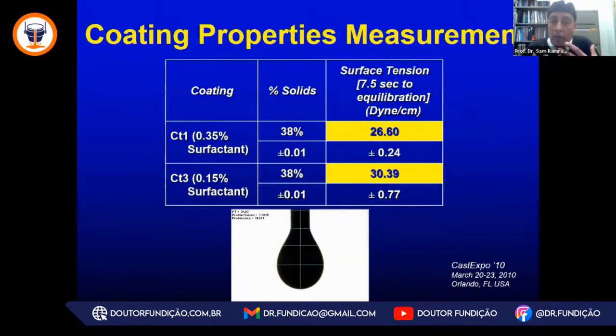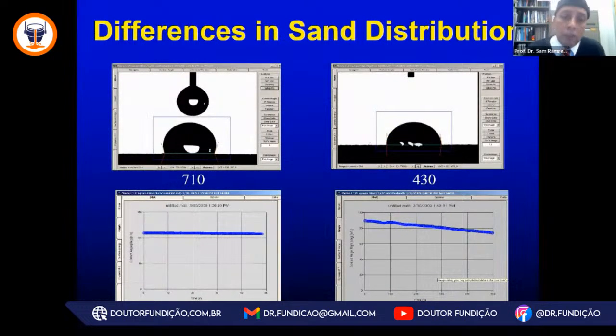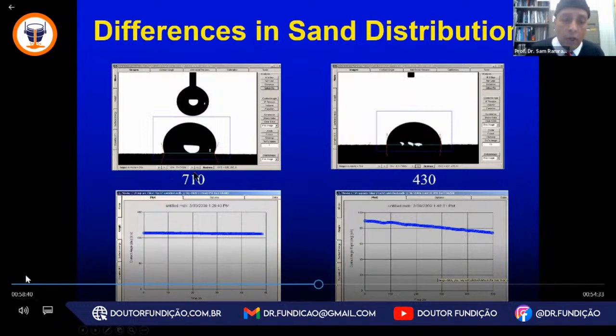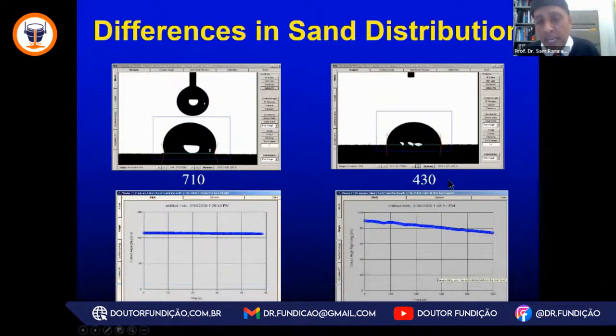We can look at some of the rheological issues on the coatings, such as the solids, the surface tension, the surface energetics via contact angle. And we have studied these coatings on these chemically bonded sand substrates. Here I'm showing the surface energetics on a finer sand like the 710 on the left versus a coarser sand on the right. For example, the 710 sand would have a 75 to 80 GFN. That's the grain fineness number. And the 430 would be closer to 50, 55 GFN.